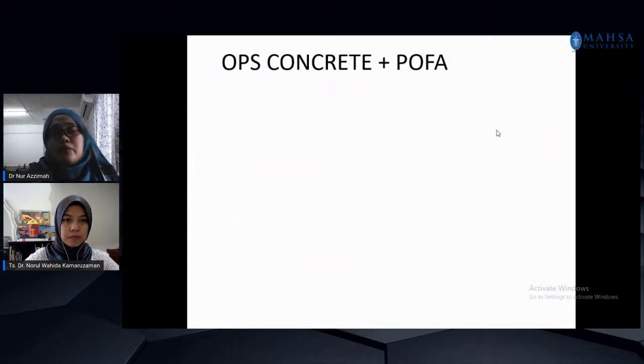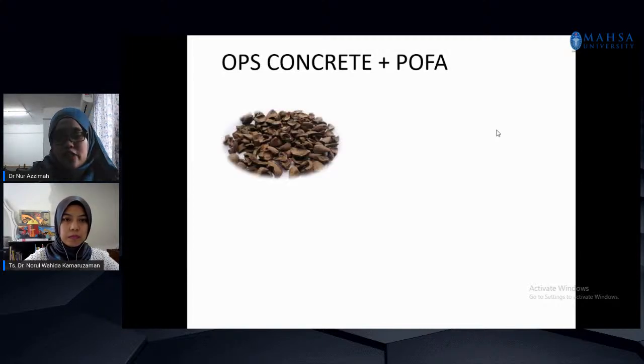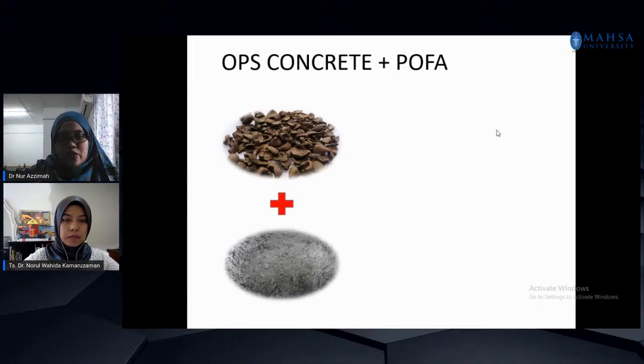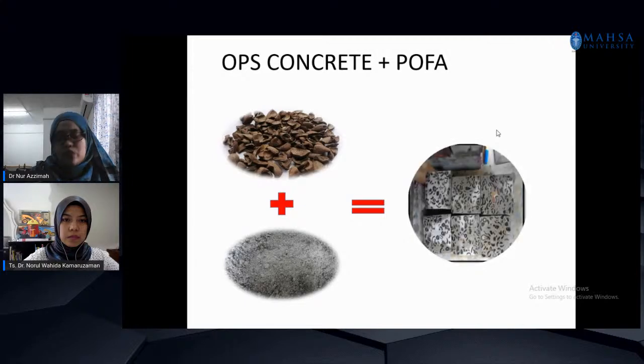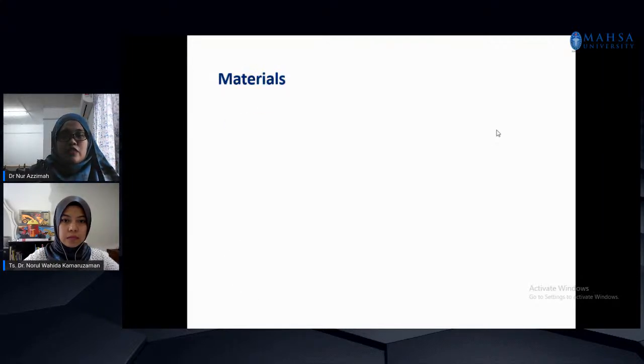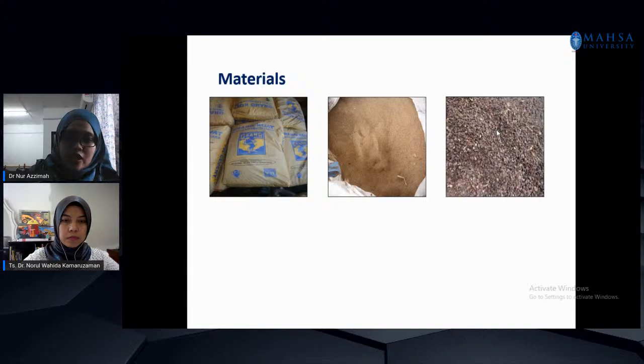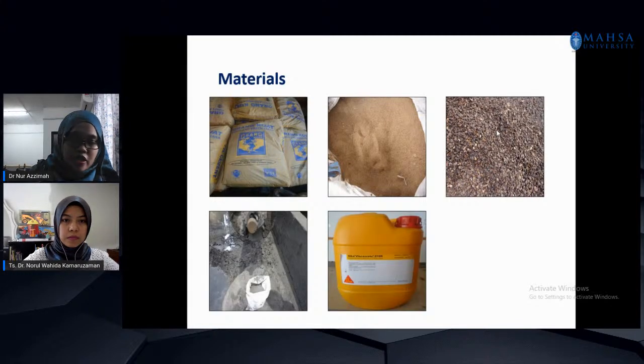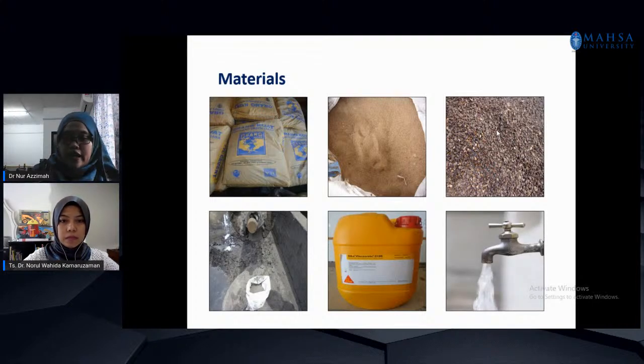All right. So what makes us different from the rest of the researchers is that we combine this oil palm shell and also POFA inside the research. Inside our research, we combine the oil palm shell and also the POFA, which is the palm oil fuel ash, and then we produce this kind of concrete. If you have the intention to try, these are the materials that we have used. So we need cement, we have sand, and then the oil palm shell, the POFA, water, and also we add on some superplasticizer, because lightweight aggregate concrete consumes a lot of water, so we have to make sure that we don't use too much water. So we have to add on either admixture or the superplasticizer to balance the water, right?